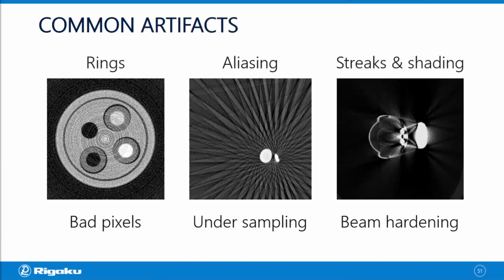Rings usually come from bad pixels or non-uniformity of the detector, and this one is easily correctable. Aliasing comes from undersampling. This means that you didn't have enough projections. And again, this is easy to fix. You just need to collect more projections. Streaks and shading usually come from what's called beam hardening. And this one is a little bit trickier to get rid of.